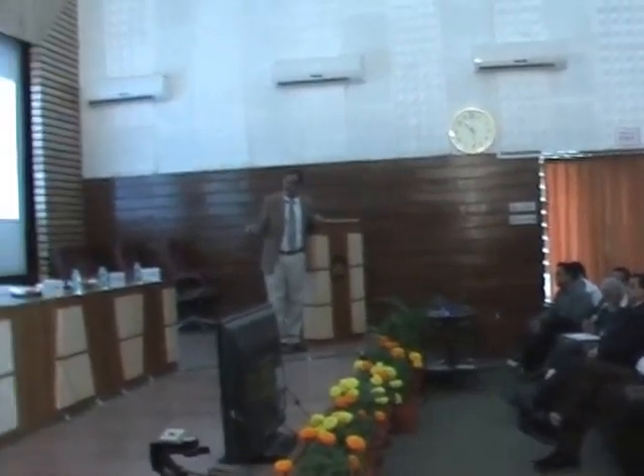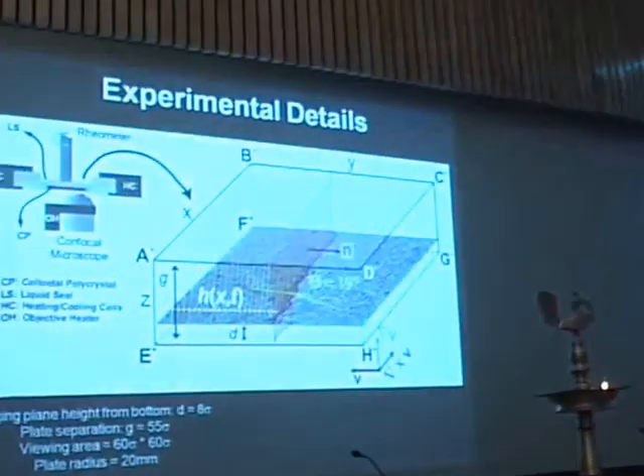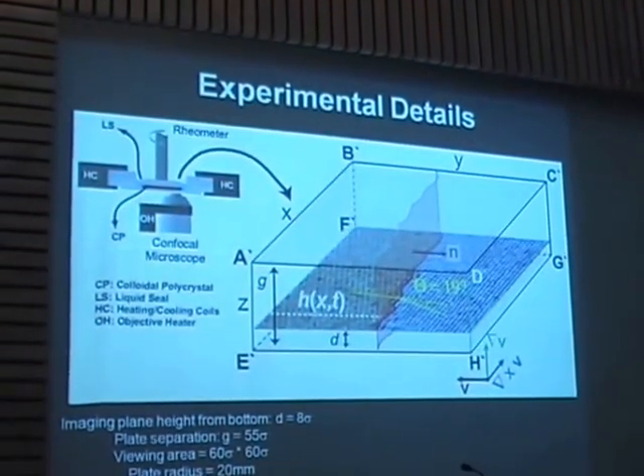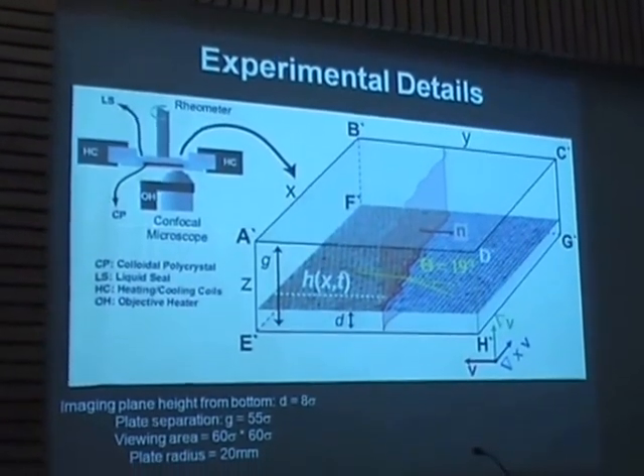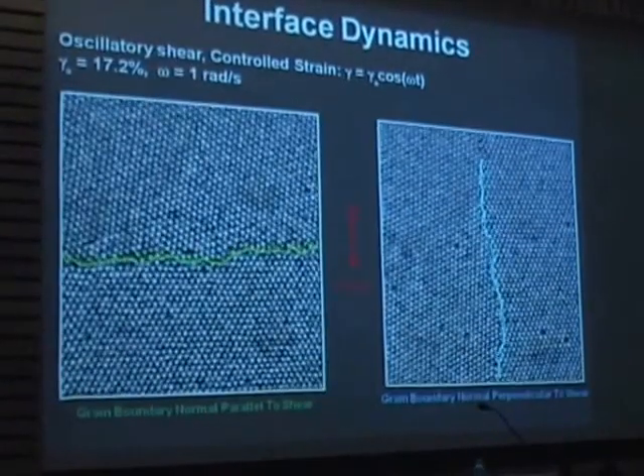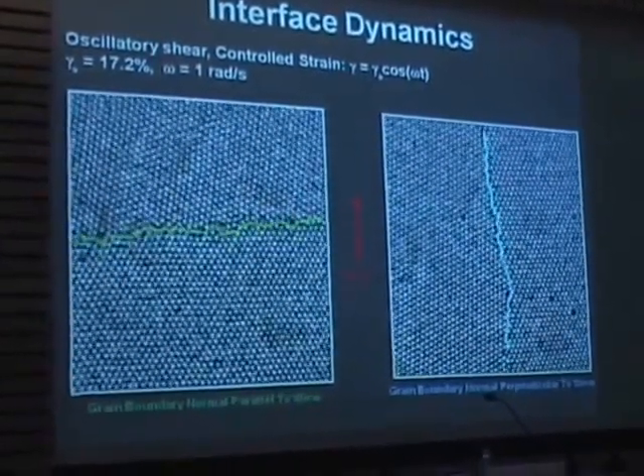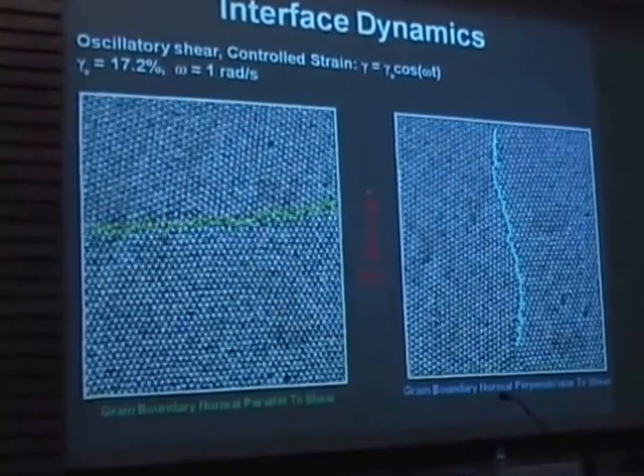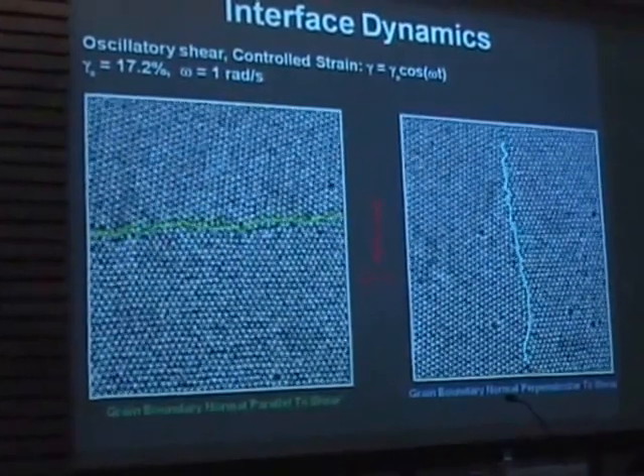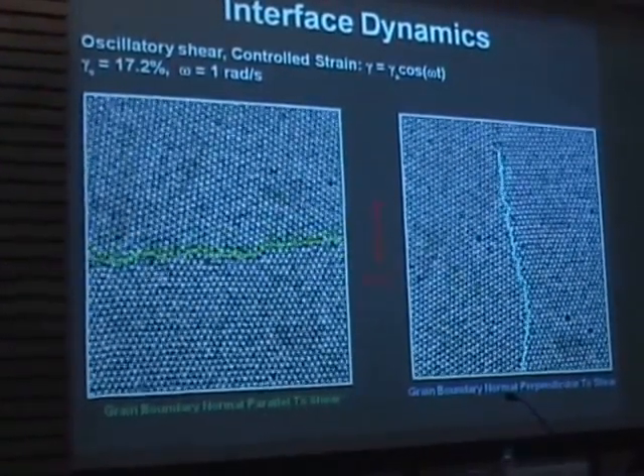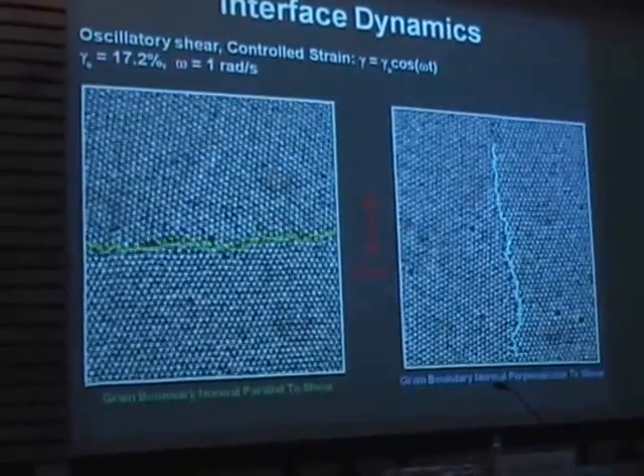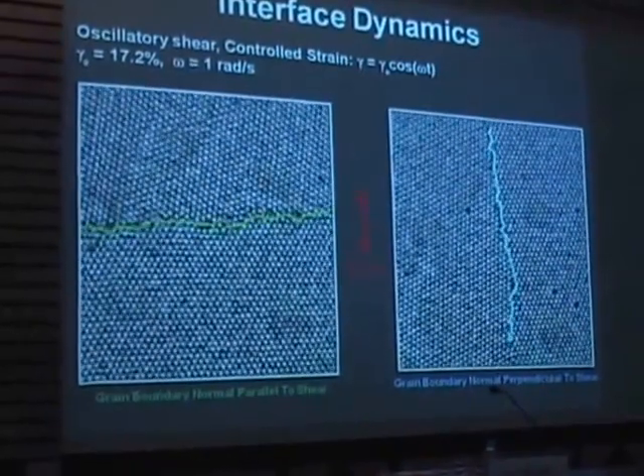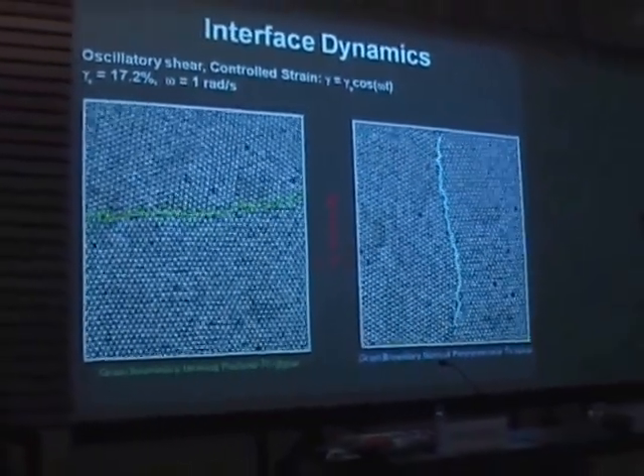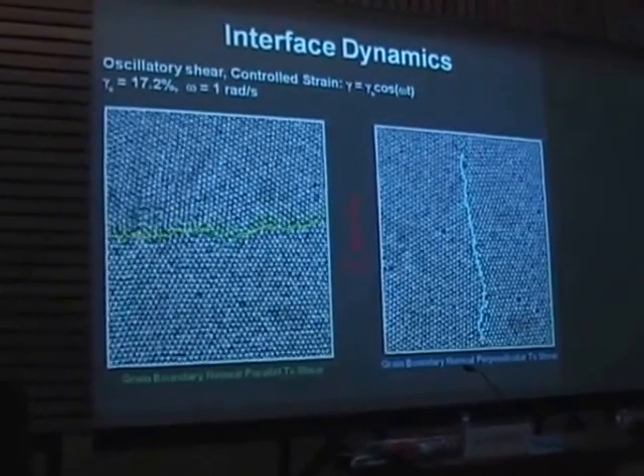So the idea is, the grain boundary between these two, how do they behave? Since I'm not going to give detail, I'll just tell the gist of these experiments, which may have some implication in engineering materials. We are now shearing in an oscillatory manner, and this is the grain boundary we are tracking. What we find is that a grain boundary, let's say the normal is this, and this is the shear direction, is very different if the grain boundary is parallel to the shear. So here the grain boundary normal is this way, which I call the grain boundary perpendicular, and this is grain boundary parallel. These experiments establish for the first time that these two grain boundaries are very different.